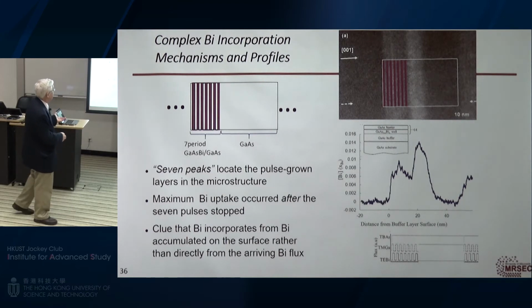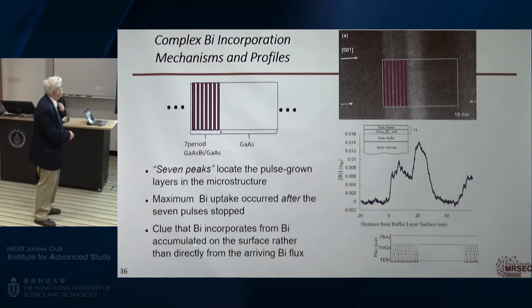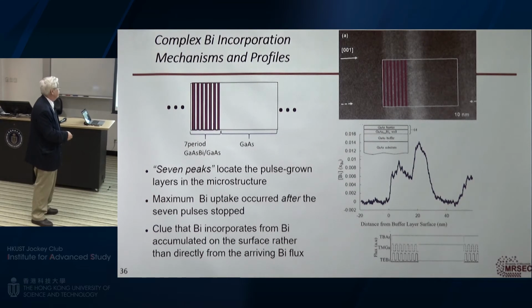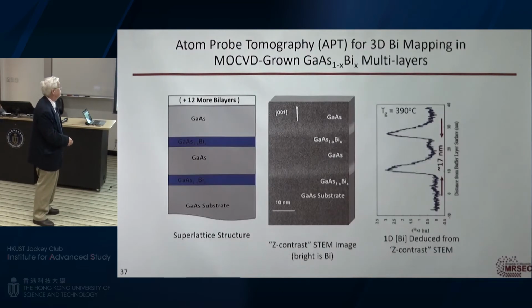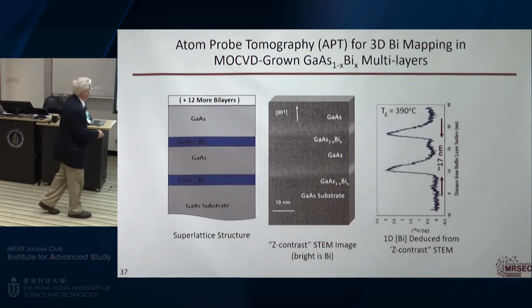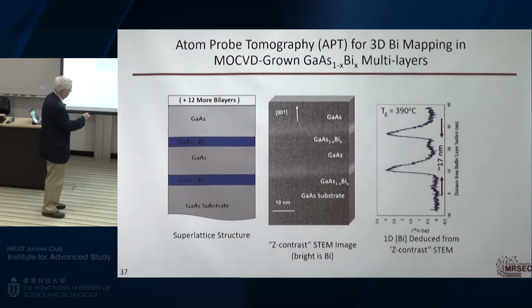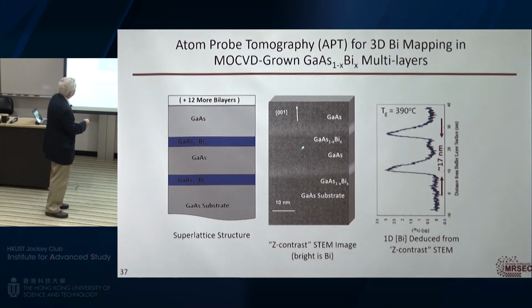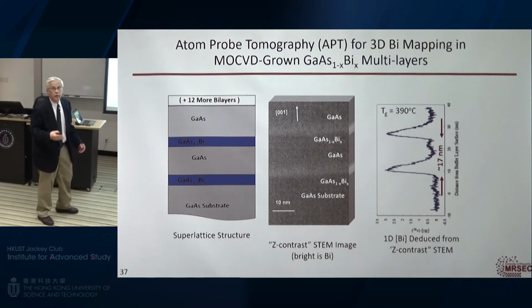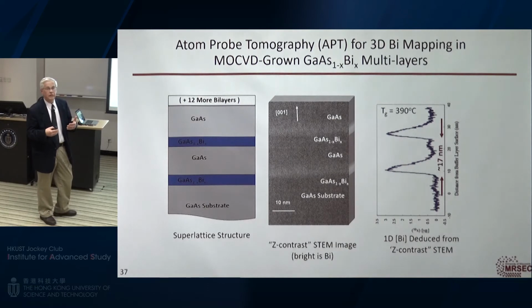So the clue is that bismuth incorporates from bismuth accumulated on the surface rather than directly from the flux. That is something happening in the surface chemistry, and we can look at this in more detail. This is a transmission electron micrograph. Here's where we're growing the compound, and all the bismuth gets incorporated after I stop. So the question is, why does bismuth go into the crystal when I don't have bismuth in the system, and when I have it in the system, why doesn't it incorporate?